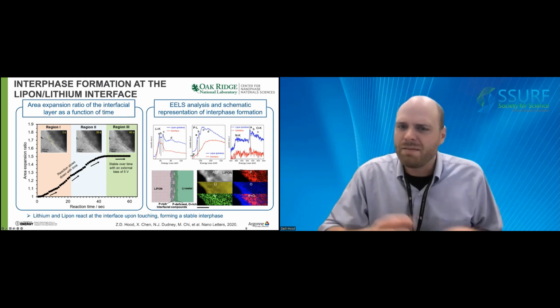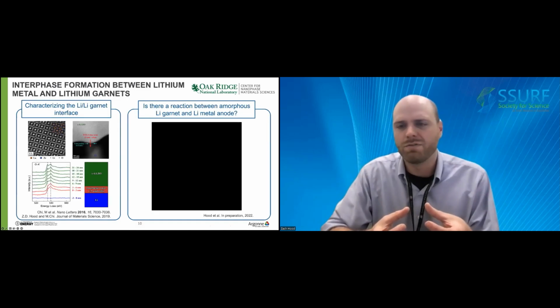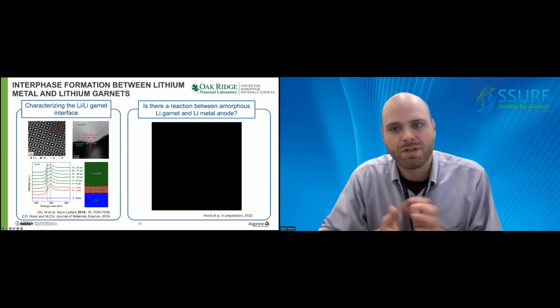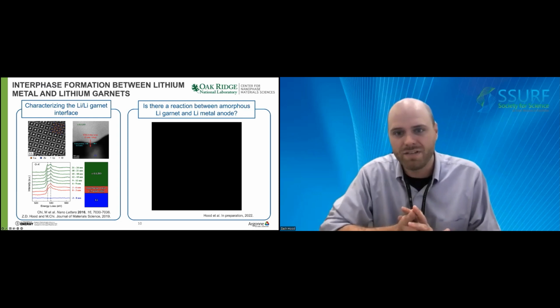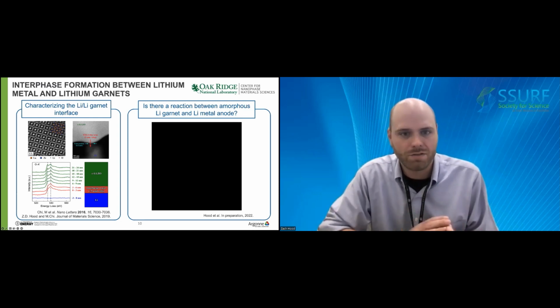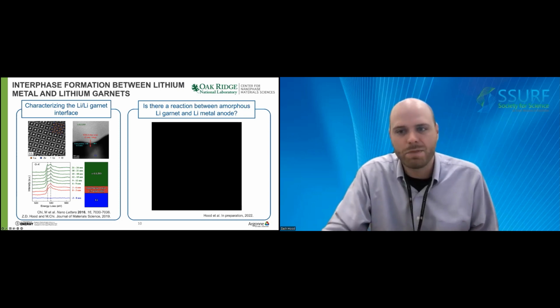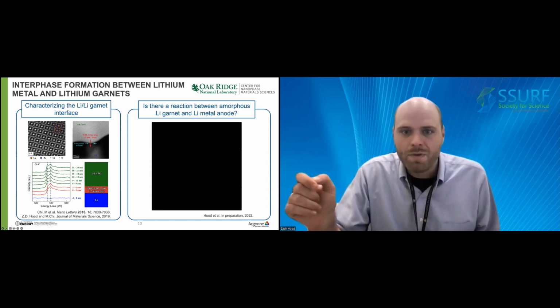So now that we know that LiPON, of course, reacts with lithium metal to form stable interfaces, we wanted to understand what happens with solid-state electrolytes that have an overall higher lithium ion conductivity, such as lithium garnets. Using the same technique, we interrogated the interface between lithium metal anode and the classic oxide-based solid-state electrolyte lithium garnet material.